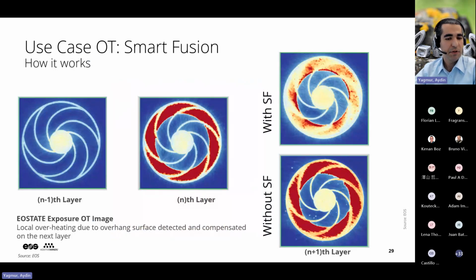In this example, we built an impeller. You see the layer n-1, and in layer n, we see a lot of new exposure areas melted just above the powder bed. What does this mean? The thermal conductivity of the powder bed is poor, so this caused a lot of excess overheating.